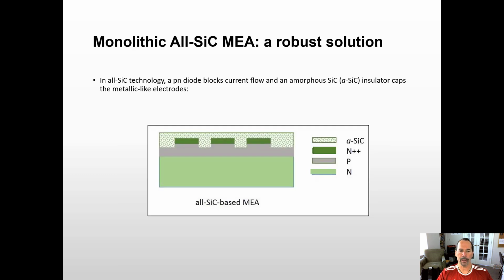So let's talk a little bit about how we would replace metals on oxide or on an insulator on silicon with all silicon carbide. So we start with a substrate. In the case of using bulk hexagonal silicon carbide, like 4H silicon carbide, we would take an N or a P-type doped substrate, doesn't matter the polarity. We'd grow a P- low doped, hole-rich layer.